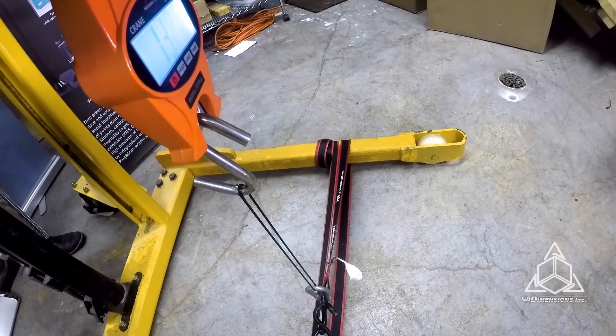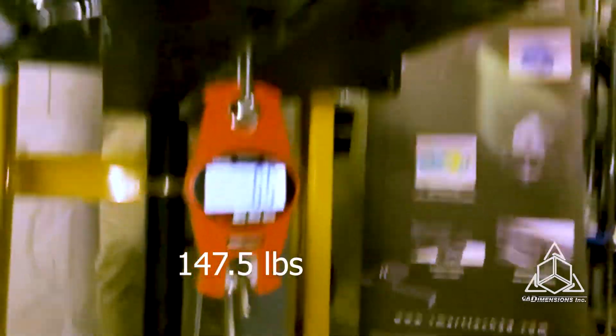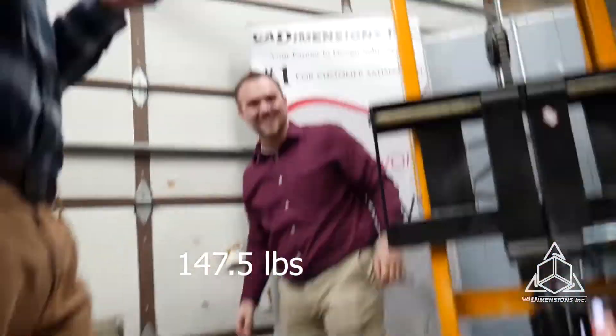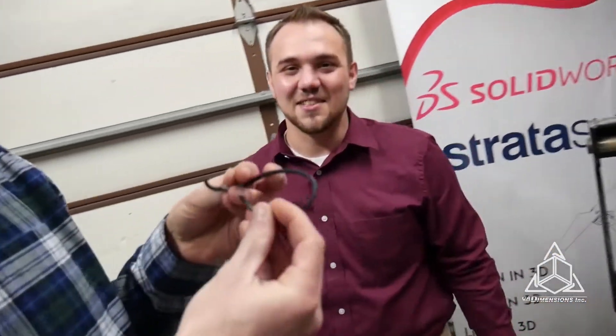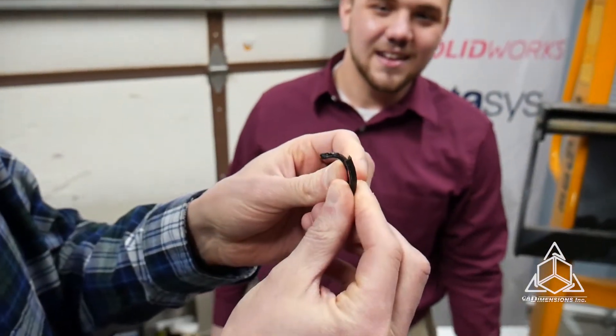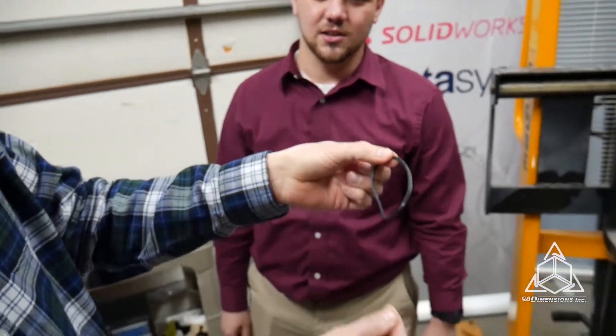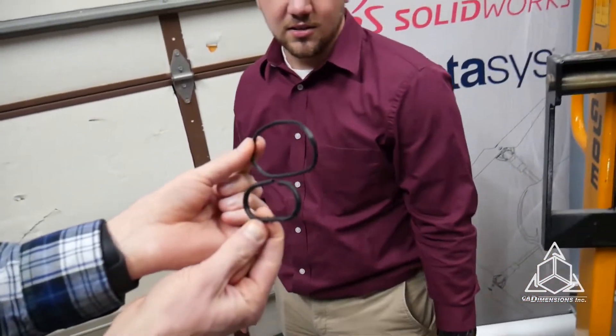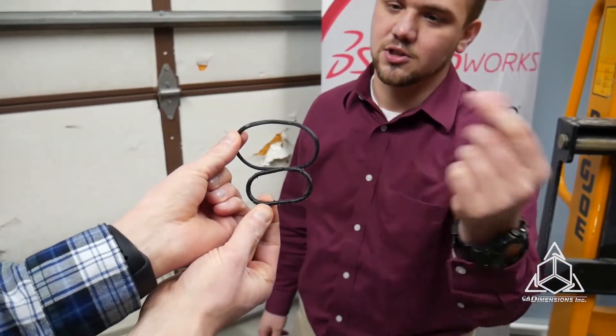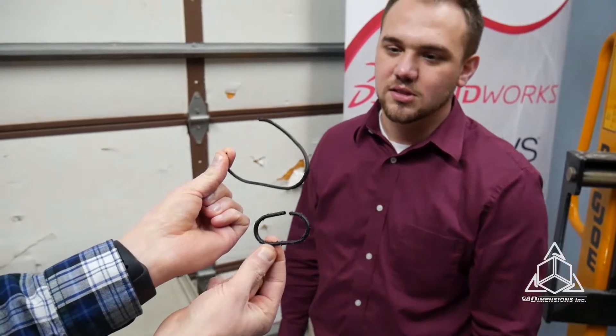One forty-five! That was a lot more than I was expecting. Look at that — it flew when it broke. And it's just frayed, which is cool. It held up a lot longer. If you look at the original shape and then compare where we started, that's how much stretch you had — a huge difference just based on part orientation. That was the only change between these two samples.